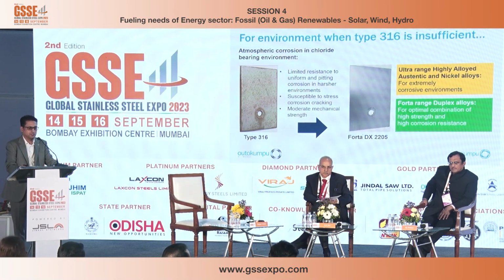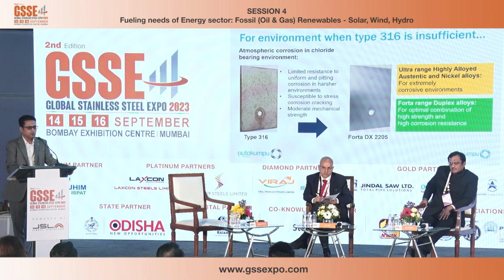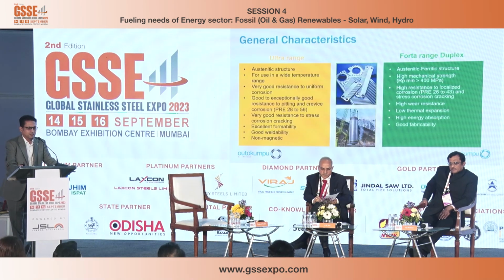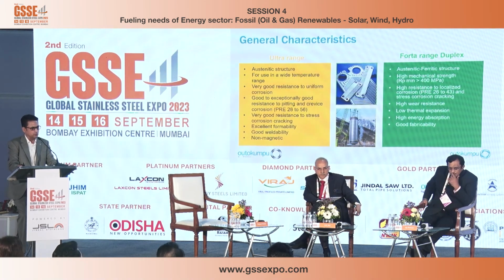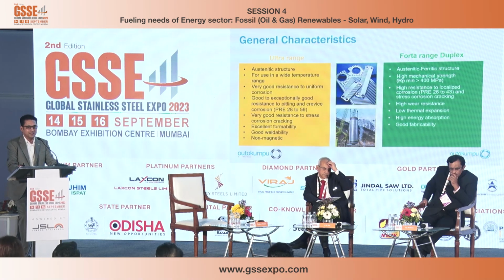So the solution you have is either you shift to the ultra high alloyed stainless steels or nickel alloys, or you go for the Forta range or duplex stainless steel, where you use the higher strength or higher corrosion resistance or a combination of both. Talking about the general characteristics of ultra grades and Forta grades, ultra grades are austenitic, non-magnetic, can be used in a wide range of applications and temperature ranges, with very good resistance to uniform corrosion, and good to exceptionally good resistance to pitting and crevice corrosion.